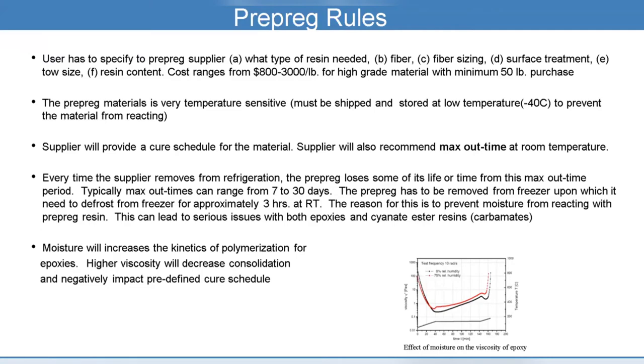Moisture will increase the kinetics of polymerization for epoxies. And you're also going to have higher viscosity, which will decrease consolidation and negatively impact the predefined cure schedule. So again, you're going to have some issues that need to be considered. And you can see here the effects of moisture on the viscosity of the epoxy. On the y-axis, I have the viscosity. On the x-axis, I have time. And so definitely there is an effect due to moisture, and that needs to be considered in your assessments.